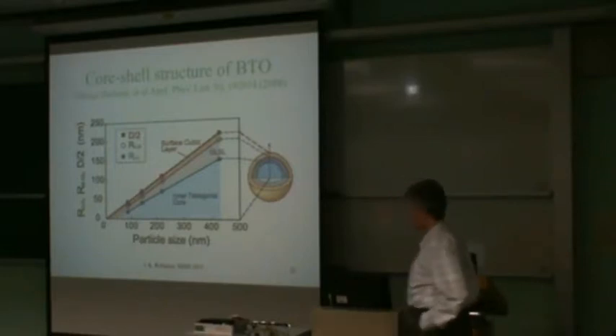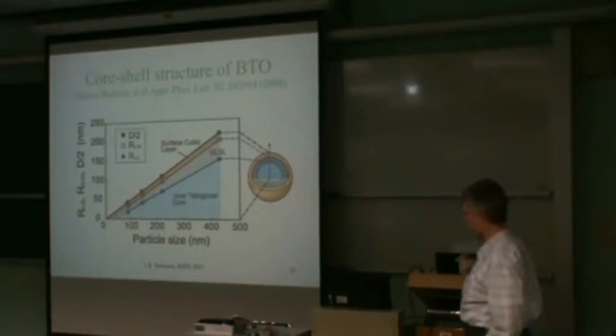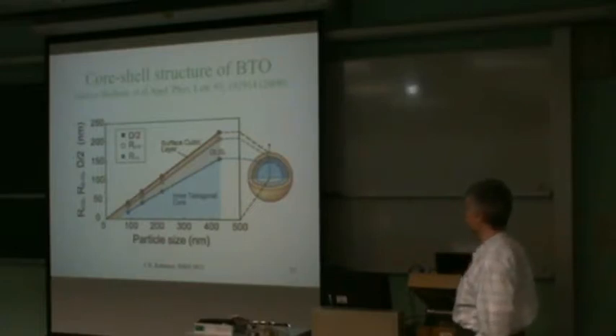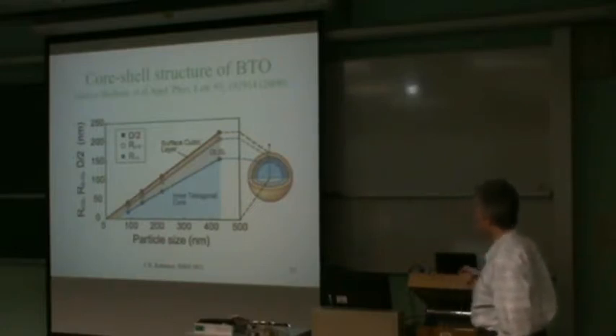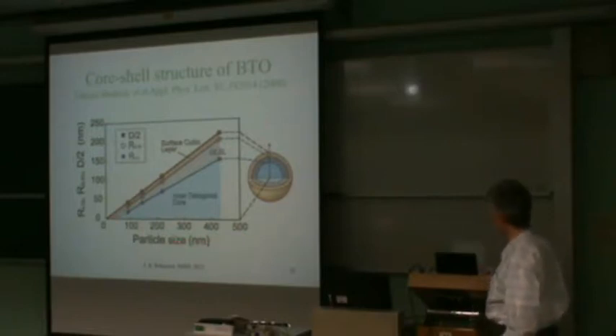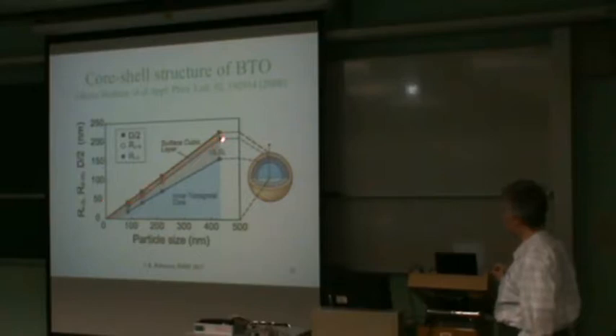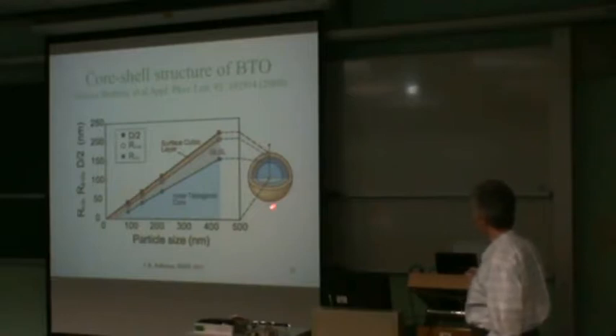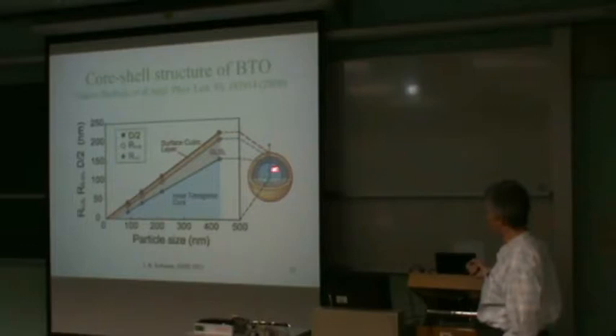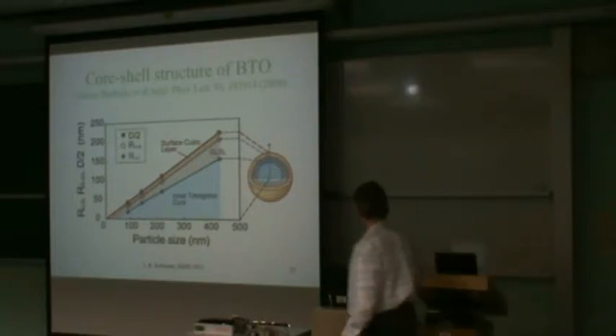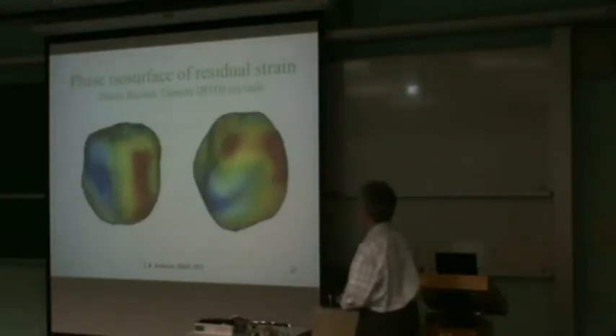The interesting behavior here that's the basis of the technology is that nanoparticle barium titanate has 3 times the dielectric constant of bulk barium titanate. And the reason for that is explained by this piece of work here, which is based on powder diffraction. But they're arguing that the inner part of the particle is tetragonal, which is the normal state of barium titanate at room temperature. But the surface has got a cubic phase present, and there's some sort of intermediate in between. But we view this in the coordinate system of the Bragg peak, and we're going to show an image of this measured by this method.